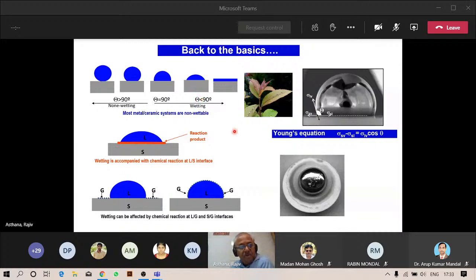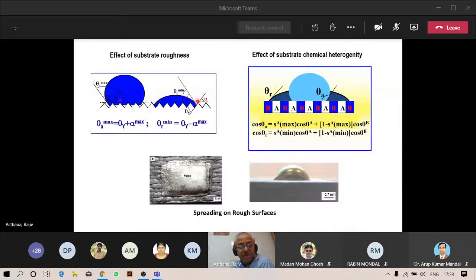Other challenges that are encountered are basically from roughness on the surface or chemical inhomogeneity. The surface of the solid might be chemically inhomogeneous, and that will affect the spreading and the contact angle. In composite materials, especially when you're dealing with ceramic materials, ceramic composite, even after grinding and polishing, the surface is not perfectly smooth. So the spreading droplet may not be completely round. It could be an anisotropic spreading, and that makes the measurement of angle of contact challenging.